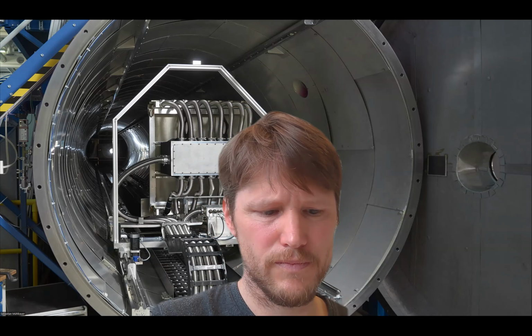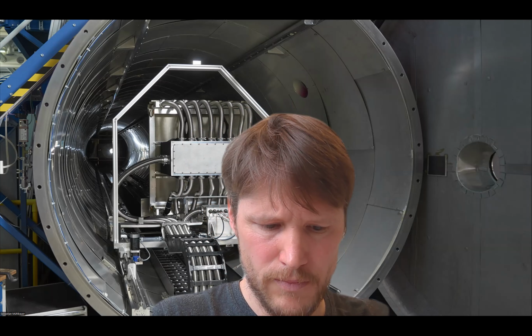So there are several reasons that we can deform or observe an anisotropic vortex lattice structure. One of the causes would be, for example, rotating our sample with respect to the magnetic field. And we will see some anisotropy or elongation of the structure in one certain direction. Then also, as in the case that we observed on YBCO, the structure may be changing along the field due to anisotropies of the penetration depth along a certain direction, or it can be caused by the movement of the nodes that we mentioned before.